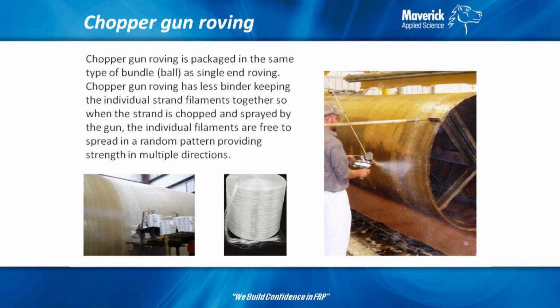Some of the difficulties with this is if you do it by hand, it's very difficult to coordinate how much you're getting on in place. If you use roll goods, you know you're getting 1.5 ounces of chop strand mat in that location. Depending on how well calibrated that guy's hand is whether or not you'll get 1.5 ounces per layer if he's doing it by hand.